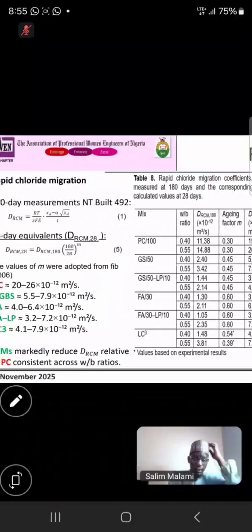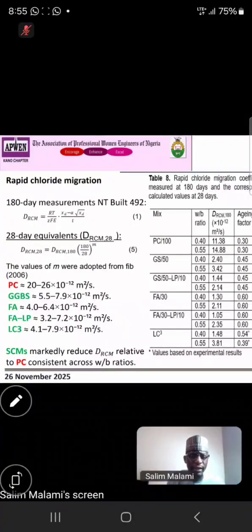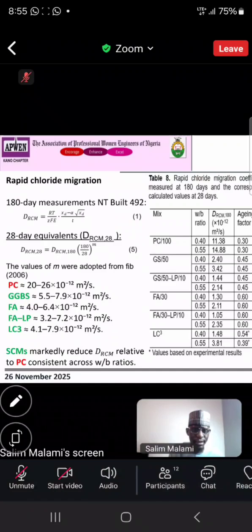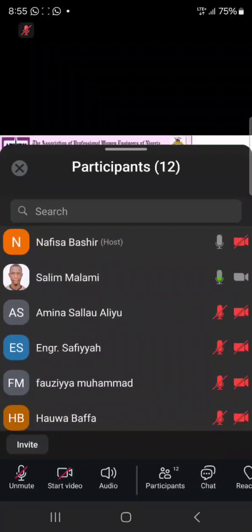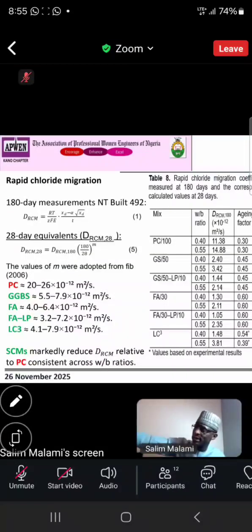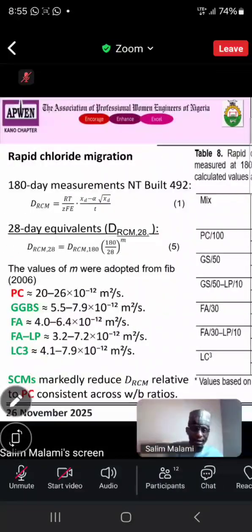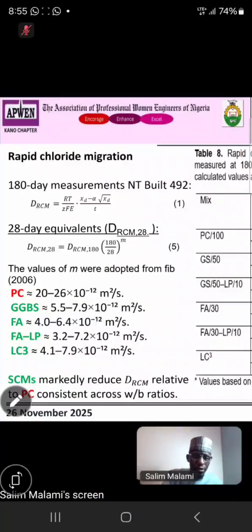So then, rapid chloride migration test. We took the rapid chloride migration test after 180 days. The reason why I do this at 180 days is because of the hydration that is occurring in the concrete. So I just want to see the effect of hydration. So I left the sample, that is the cylinder, inside the water for 180 days. Then I took the test, then I calculated the depth of the chloride, then I calculated the rapid chloride migration using this formula given by NT Build.